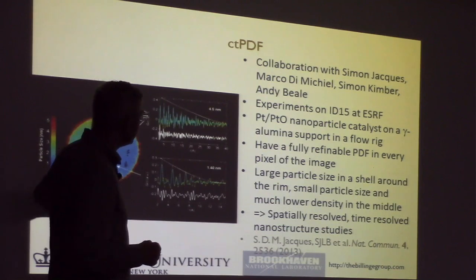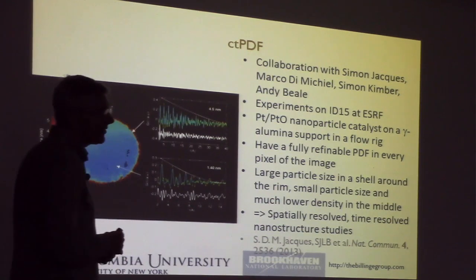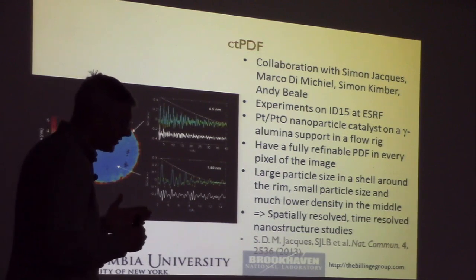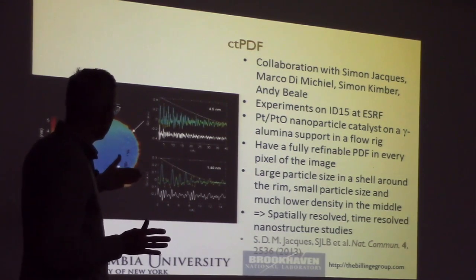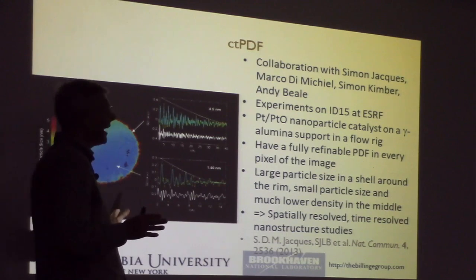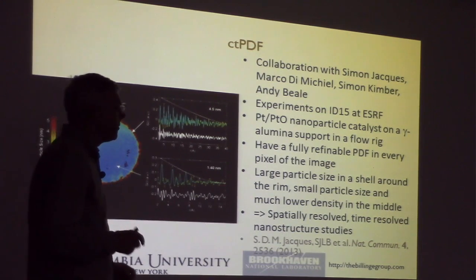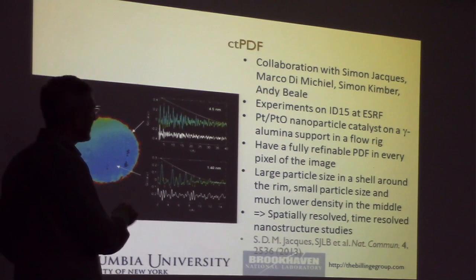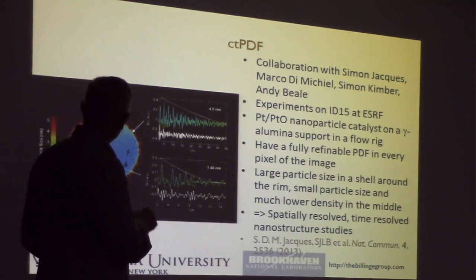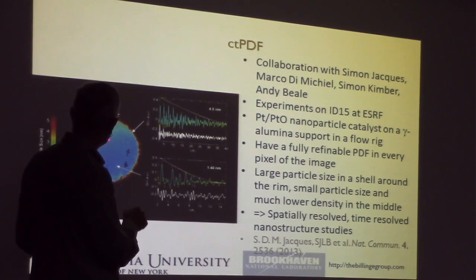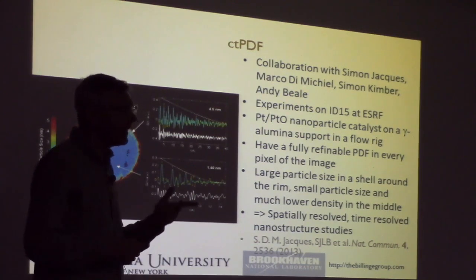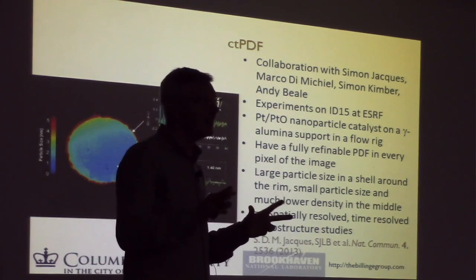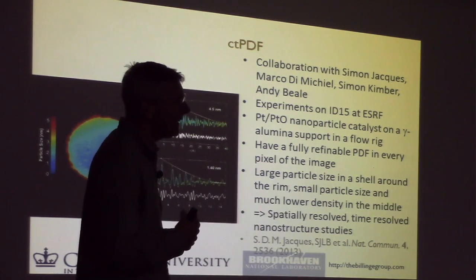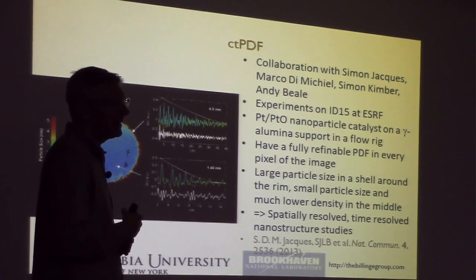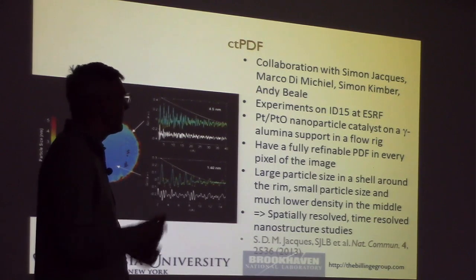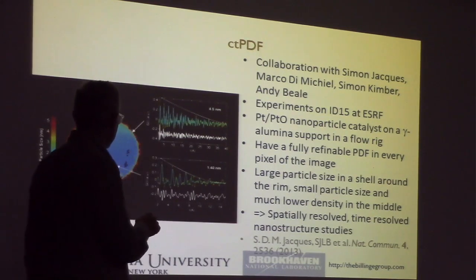So we run it through the tomographic reconstruction. So instead of 10,000 data sets, which are the average projection, average through some projection, we end up with 10,000 pixels. Now, this pixel is red, and this one's yellow, and this one's blue. And these colors represent numbers, so scalars. So most tomograms you see are basically scalar maps. They're maps of numbers.